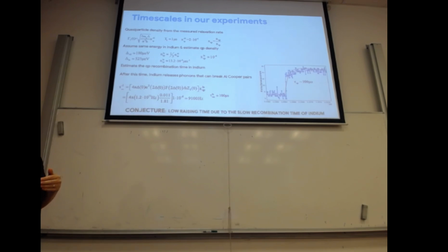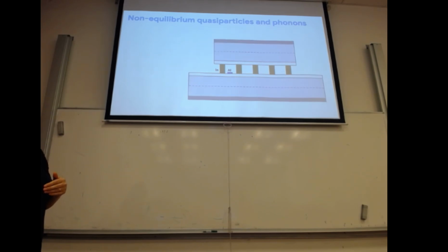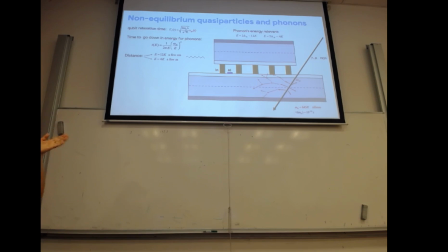So what happened with this chip is the following, right? You have your indium bumps, you have the aluminium, the cosmic rays arrive, and it starts to put out this charge and phonon. Phonon goes very quickly, the heat, and goes into the indium. The indium is a sort of absorber, right? It absorbs something and then it releases. And that is why we think you have this retardation effect.